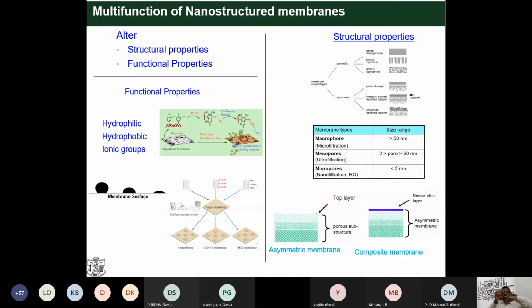Due to the pores, the hydrodynamic diameter of these gas molecules, they try to go inside the pores. Once they start to move on the wall of the pore, if they get attracted by this surface, the surface captures the molecule on the wall of these pores. Then we apply the pressure. When applying the pressure, they easily transport through the membranes. That is called one of the functional properties.